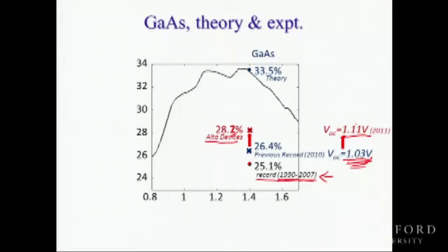And it entirely impacted the voltage from that formula from Shockley. It's the ideal minus kT log of the extraction efficiency of fluorescence. Even at 1.1 volts, that translates to maybe only 10% extraction. So there's a lot of room, and the theoretical limit is more like 1.15. And actually, Alta is headed there.